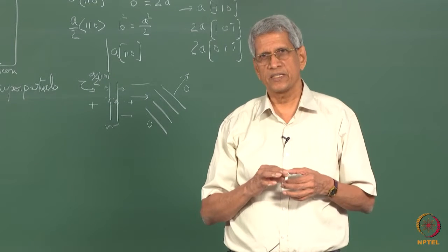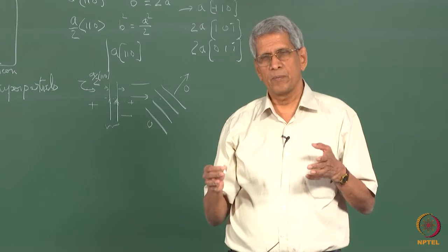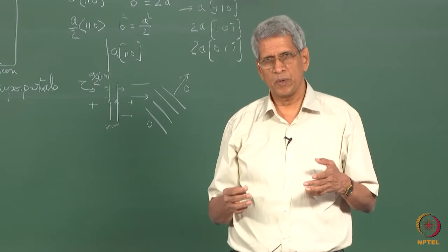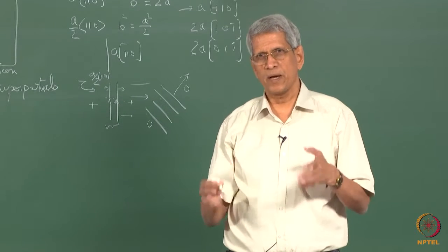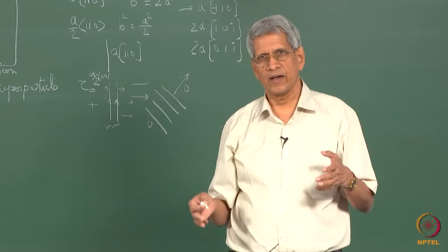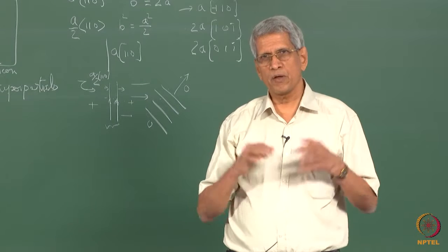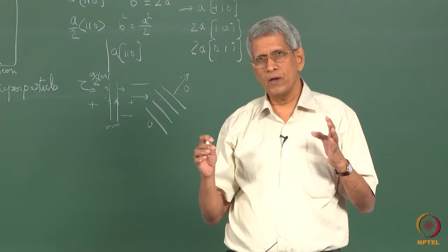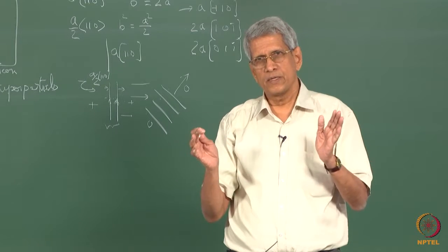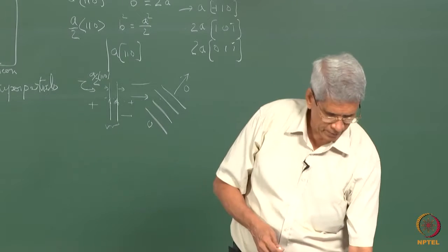Another type of structure is where a superpartial as well as a perfect dislocation of the desired lattice can be present. There is a third case where the superpartial itself can have different magnitudes. Depending upon that, the number of superpartials required to pass through the lattice to restore order can turn out to be more than 2.